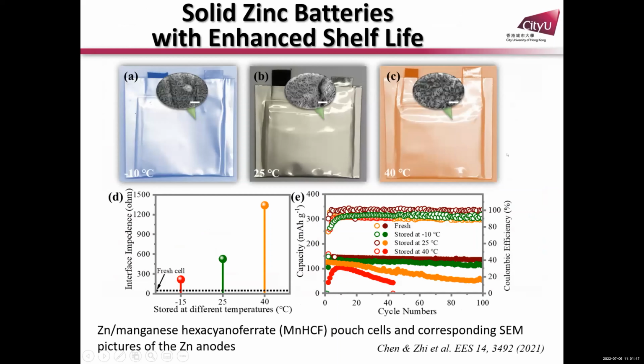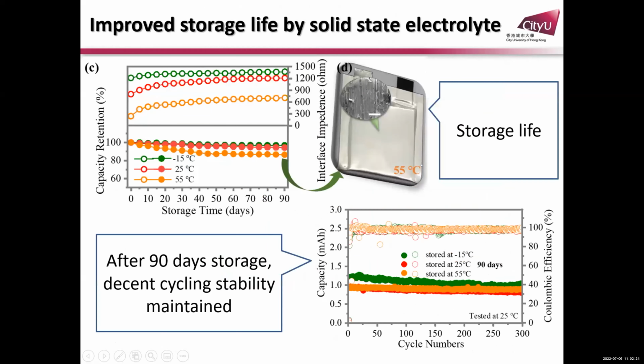Another issue is storage life. Sometimes we call it shelf life. Shelf life means you assemble a battery and store it at different temperatures. Even if you don't test, if you don't do cycling, after a few days, say 1 week, you will see the capacity will be lost. And with zinc in mild electrolyte, you will see something growing on the zinc, especially when the temperature is getting higher. Let's say the storage life of a zinc battery is not good.